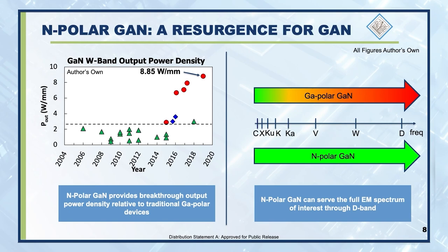And I'd like to conclude with saying that gallium polar GaN has performed extremely well from C band to K band and up to maybe Ka band. And its performance is more and more challenged as it goes to higher and higher frequencies. Nitrogen polar GaN, on the other hand, performs well from C band all the way to D band. And so it can serve the full EM spectrum of interest through D band.